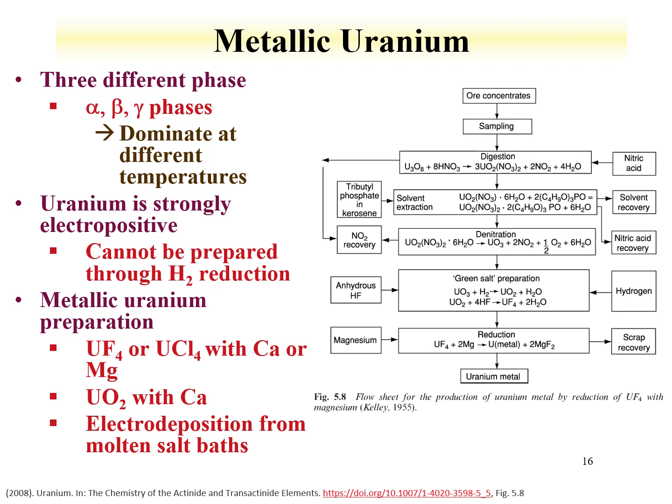As we already discussed, if I want to make uranium dioxide, I can take higher oxides, treat them with hydrogen under heated conditions, and make UO2, so that's uranium-4, but the hydrogen will not drive uranium down to the metal. So that means to prepare uranium metal, I have to use a different route, and what's done is shown here, where we make fluorides of uranium.